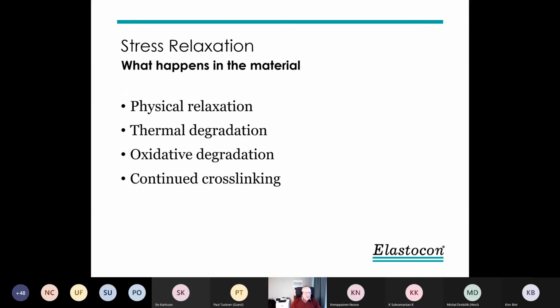If we talk about what happens in our rubber material when we do relaxation tests, or aging, in fact. If we compress or stretch the material, we have first the physical relaxation. That is only a rearrangement of the polymer chains and fillers, which will find new resting positions or places during the compression. And nothing is really destroyed. It's just the physical. That one we do not want to count in. We want to look at the chemical degradation due to aging.